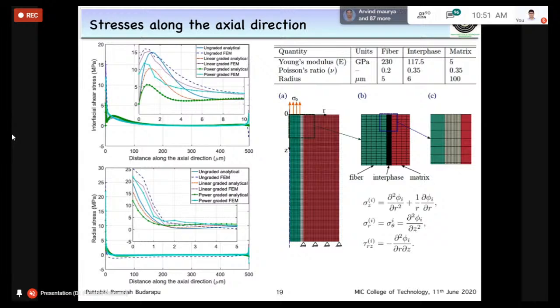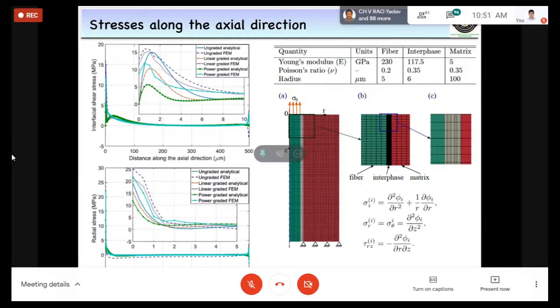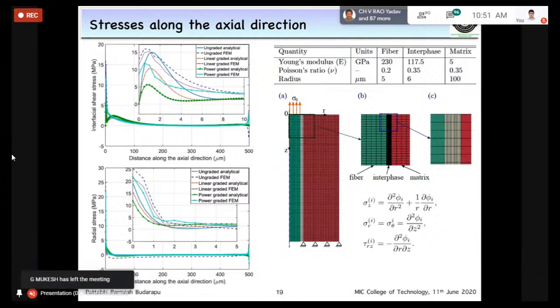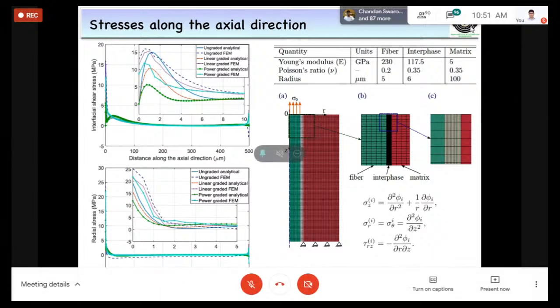Ungraded is the blue line, the orange line is linearly graded, and the green line is power gradient. You can see more or less like 20, 15, and something close to 11 or 12 for the peak stresses. That's how it began, and then it's dropping to more or less close to maybe 2 megapascals within a distance of 2 microns.